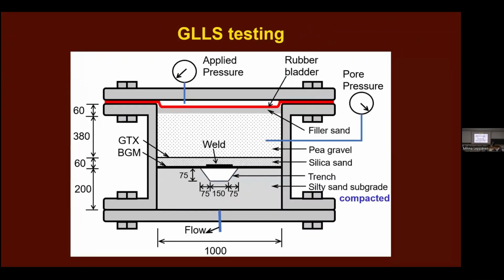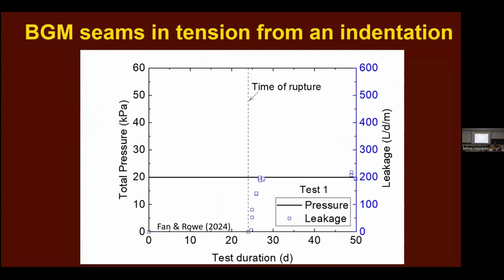Now let's put a weld over an indentation that you would get in the field and see how it performs. So we're applying a pressure here of 20 kilopascals, so it's a cover application where there's some differential settlement. And after 24 days, the seam fails, and the leakage goes from 0 to 200 litres per day per metre of weld.